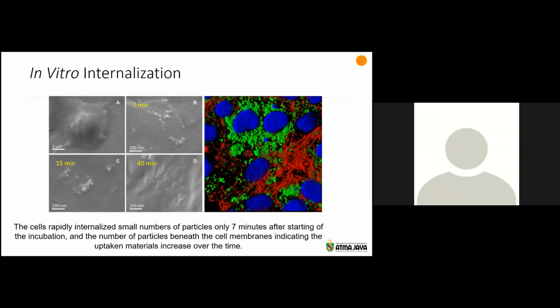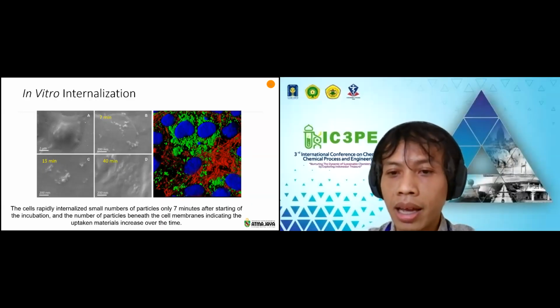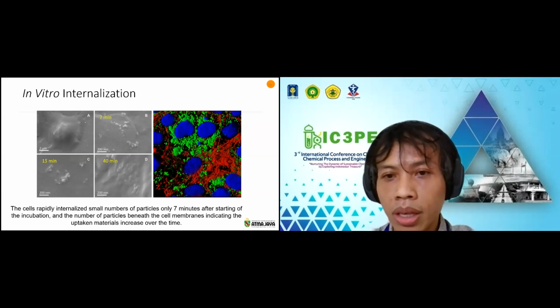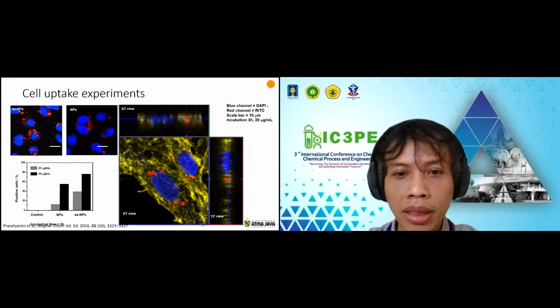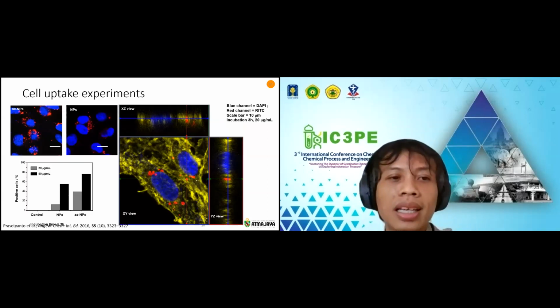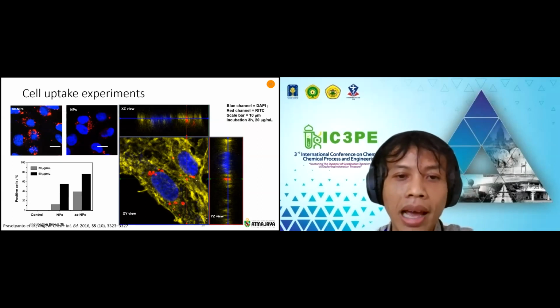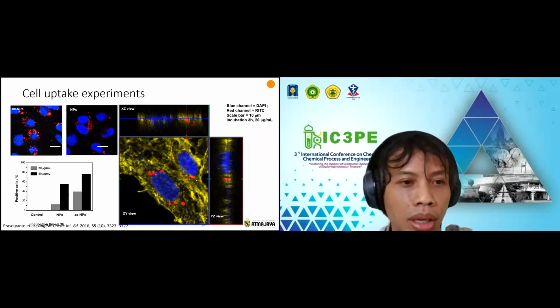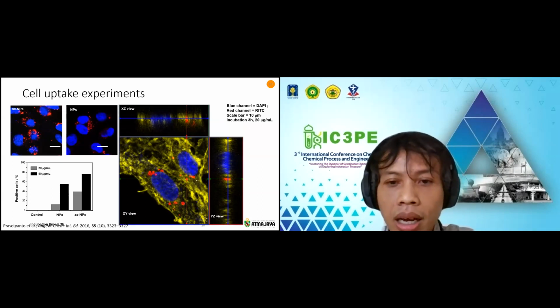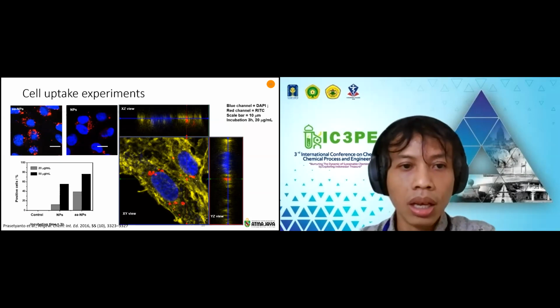On the left side, you can see that after 7 minutes of incubation, the nanoparticle slowly enters the cell, and then after 40 minutes, all of the nanoparticles we incubated together with the cells are already under the cell membrane. And on the right side, the blue one is the nuclei, but I think it's better you see in this one because here it is much more clear that the nanoparticle entered into the cells and then stays there.